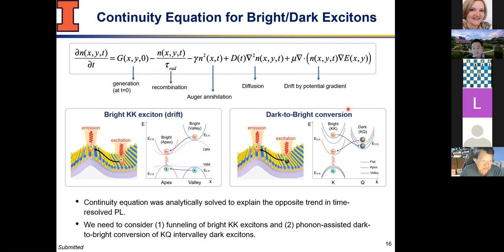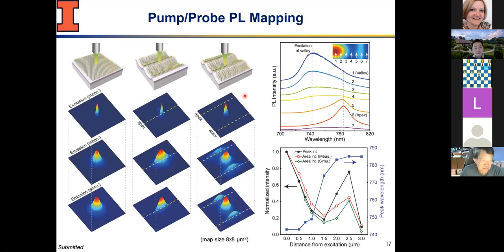There are additional processes that are interesting, but I won't talk too much about them. Just to say, if anyone is interested, there is also this effect of strain-induced dark-to-bright exciton conversion. It turns out strain is so powerful it can make those dark excitons become bright. It's related to the energy shift as shown here, but I won't go into a lot of detail. But when we consider all this with the equation that I'm showing here, we're able to predict and also explain our measurement quite well. So let me briefly show you a couple of slides of our measurement.